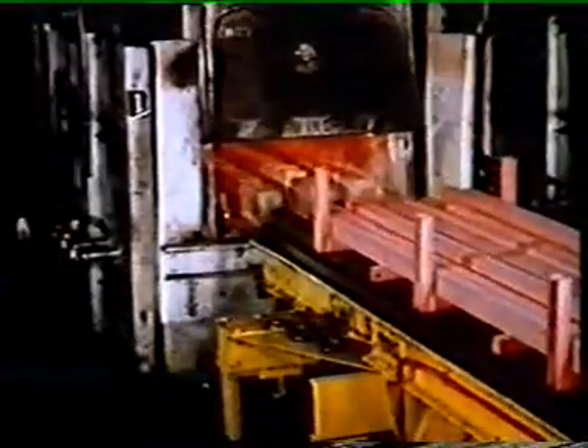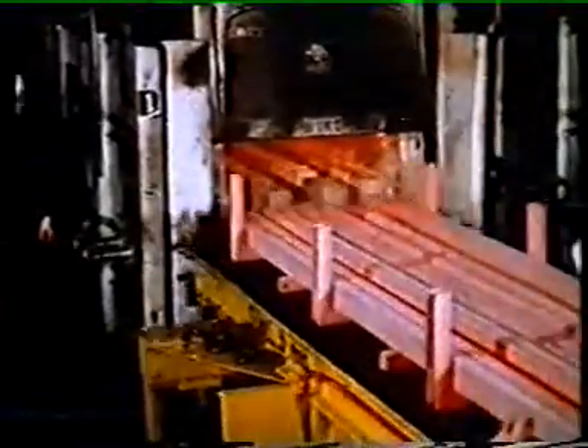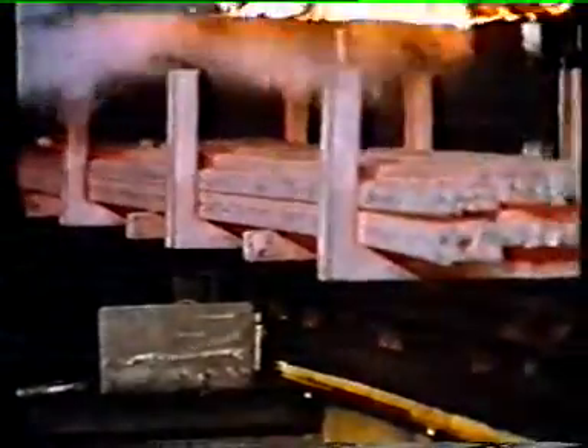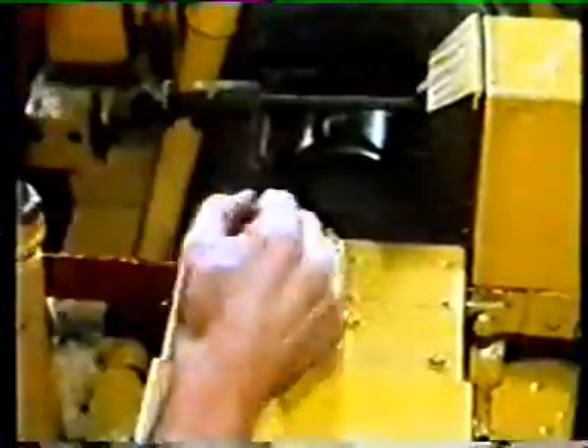When removed from the furnace, the batch is placed on a cradle above a large oil-quenching tank in which 6,500 gallons of oil are kept at an average temperature of 45 degrees centigrade by circulating it through a water cooler. Hot steel is now plunged into cold oil. The object is to cool the steel fast.